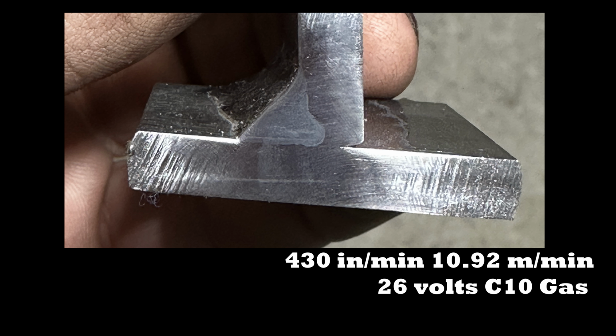Well, spray, for the most part, doesn't care how thick the plate is. If you're running high enough settings, it will fuse it. Unfortunately, to get this level of performance, you can't get it with a 200 amp MIG welder. This was basically around 200, 210 amps, but at 26 volts, and I would say better than 75, 80, 90% of the machines out there in the 200 amp class aren't even capable of 25, 26 volts. So right away, that's a no-go. And you're going to melt down the components in the welder if you do any volume, even if it could do 25 volts. All right, let's move on.